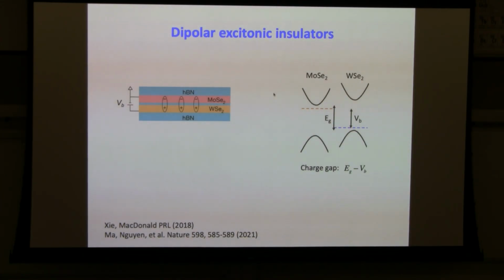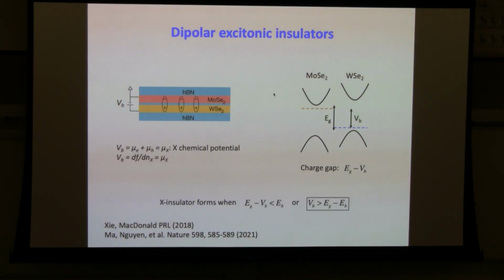So the effective charge gap of the system under a bias voltage is no longer Eg, it is actually Eg minus VB, because the VB reduces the effective charge gap for charge excitations in the system. So now, by tuning this bias voltage VB to tune this effective charge gap to be smaller than the binding energy of the excitons, then you can spontaneously populate a fluid of excitons in the system, which are illustrated like this. Electron will be in one layer, hole in the other layer, and they just bond together to form this boson.